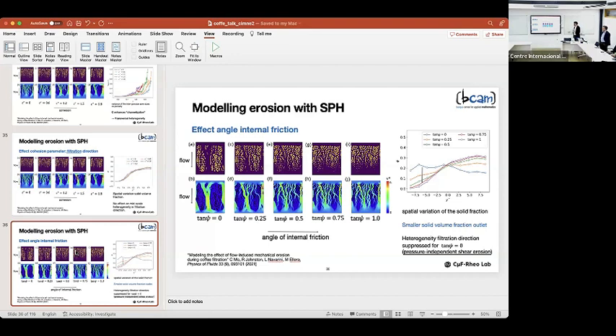I don't quite understand how you obtain the permeability of the fines. So most of the resistance increase comes from these fines accumulating in this layer, right? And what I understood was each fine is fixed at a certain point, and it just adds to the resistance through the Stokes law. In the first part of the model, we model the resistance of the fines by fixing them in space, and therefore with a flow going through a certain portion of fines, yes, it will increase. So basically, I remove a fine and it reaches a point. I decide it's the end of its path and it stops there, and then it just keeps adding to the resistance because of Stokes law. The resistance will increase as long as they accumulate more. Yeah.